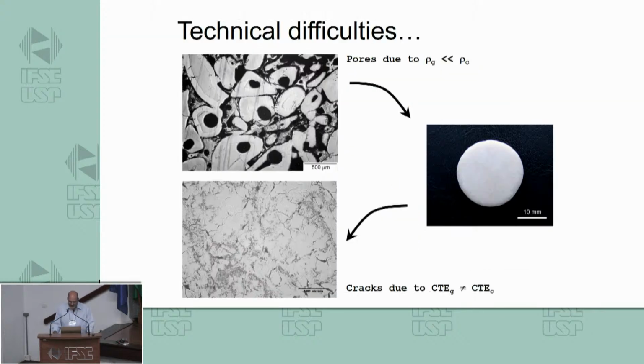And technical difficulties, as I said to you, if you have, like here, glass density much smaller than the density of the crystallized phase, you have the crystallization from the surface. Here, the crystallization from the surface was too fast, so we were not able to densify. Here we have the resin, so we have the residual porosity due to incomplete densification, but we also have the pores due to the difference of density of the present phases. So this is an issue.